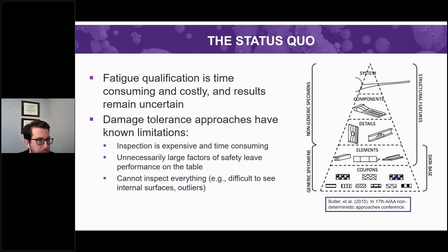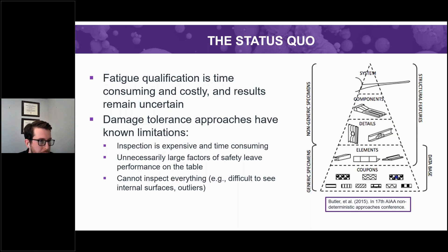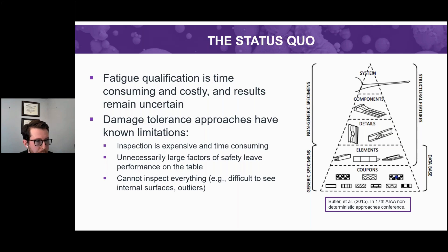The standard approach to understanding fatigue in engineering materials is to qualify materials, processes, and components following the traditional pyramid of pain. Typically hundreds to thousands of tests are done at the coupon scale to determine design allowables — testing individual tensile coupons, then scaling up to elements, details, components, and ultimately full flight systems testing. This approach is obviously very costly and time-consuming, particularly for fatigue, where you have to run tests for hours and days as opposed to tensile properties, which are much more straightforward to test.